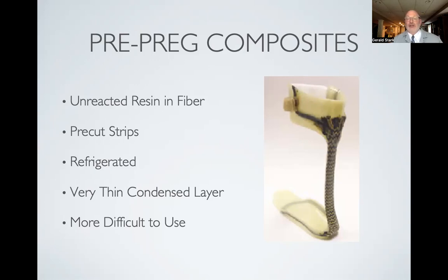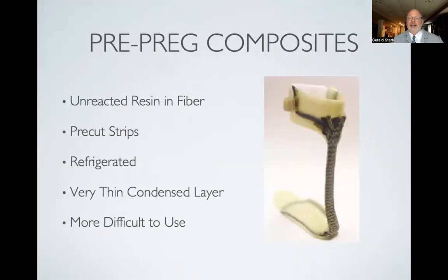The prepregs have a very thin condensed layer, and they can either be in the carbon layers themselves, or they can be sandwiched in with little cookies of this refrigerated resin that you can place and cut in between the carbon layers. This particular brace, this particular orthosis, has a combination of fiberglass, e-glass, and carbon to create it.